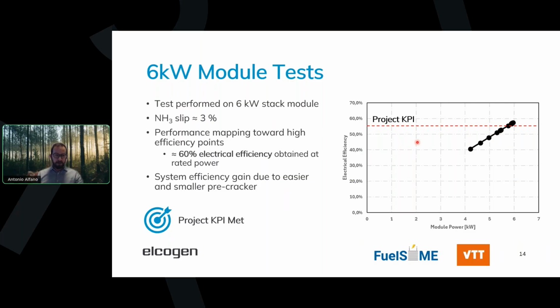And to make sure that you would crack completely the ammonia before reaching the stack, you would need to really sacrifice and oversize also the pre-cracking units. But if you have a stack which is actually tolerant to some of the ammonia, you could still optimize your system design to maximize the overall efficiency.